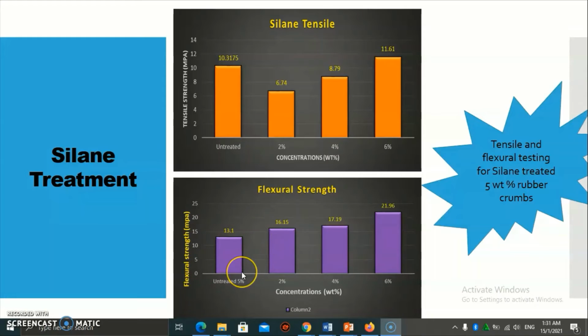Untreated is the lowest because there is no treatment inside, so it is better to use treatment to enhance the strength of the rubber composite. The strength of the 6% increased by about 12.5% higher than untreated. Okay, for the flexural testing, the increase at 6% is around 67.6% higher than untreated in the flexural strength.